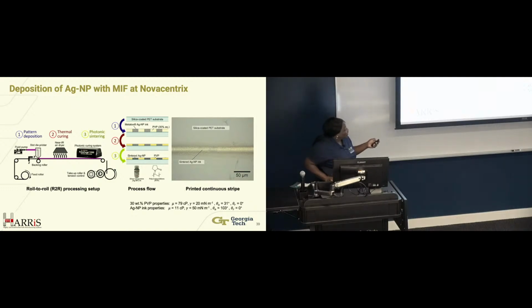And so, similar to what we did with the PEDOT:PSS, we found that with the silver nanoparticles, the problem was: what do we scaffold it against? We couldn't use PVA. It utterly failed because of the interfacial tension and various other properties. And so we had to shift to PVP. And once we shifted to PVP, you can see it's even more stable than the PEDOT:PSS. And this coating is about 40, I think, was this one 40? Yeah, 40 microns, roughly, maybe a little bit less.